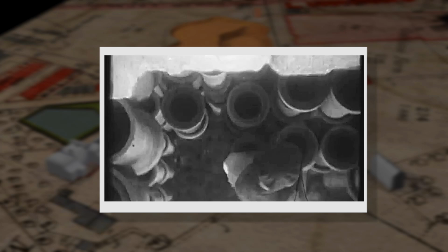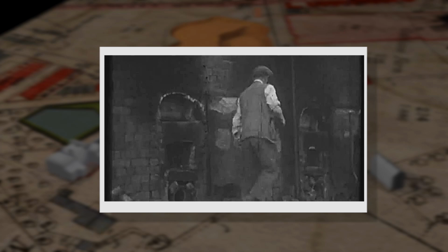After several days of drying, the clay has now turned to the consistency of a hard biscuit, and it's now ready to be carefully stacked into the kiln to be fired. Each piece has to be placed and spaced so that every part of it can be heated and eventually coated in the salt glaze finish. Any mistakes here at this stage of the process could mean the total loss of several days' work in a bad firing. The kiln is then sealed with brick and clay and then fired.